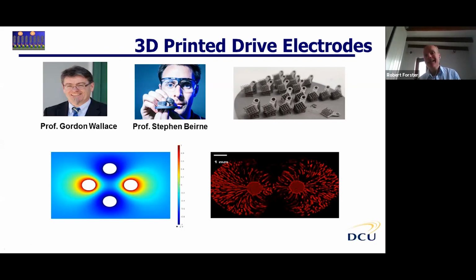If they encounter a positive electric field, then they become oxidized and can emit light. What we're doing here is leaving the shutter of the microscope open for a long time, and these trails are actually the movement of the particle over time in response to the electric field that we're generating, and the fact that there's a positive potential induced on them by the electric field.